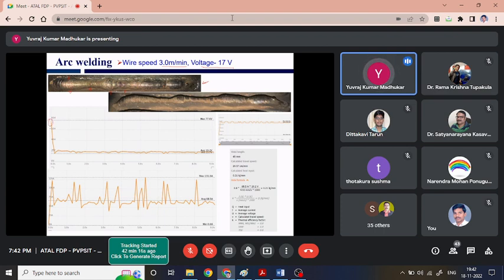Now what we did was record the welding parameters in situ. Welding parameters means welding voltage and current. Here we could see, since MIG is a constant voltage process, once the arc has been stabilized the voltage becomes almost stationary, close to what we commanded, though it has gone relatively higher, 19.2 volts. However, the current keeps fluctuating throughout the deposition. It's basically because probably the amount of energy we are giving is not sufficient, and the wire feeding rate is relatively higher compared to the energy we are giving. Because of that there is probably a short circuit between the wire and the base plate, and in order to break the circuit and keep the arc stable, the machine automatically increases the current.